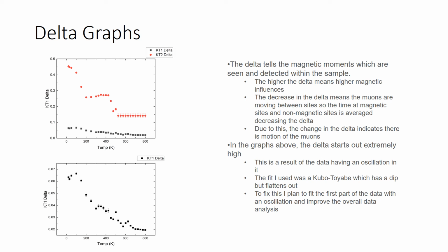In the future, I plan to fix this by fitting the data with a Kubo-Toyabe, but also for the first part of the data in the lower temperature range, adding a frequency oscillation so that it can fit the oscillation better. And then afterwards, I can turn that signal off because that specific site is no longer there, and I can just use the Kubo-Toyabes, which will yield a better fit.